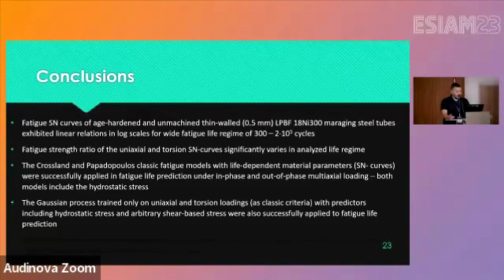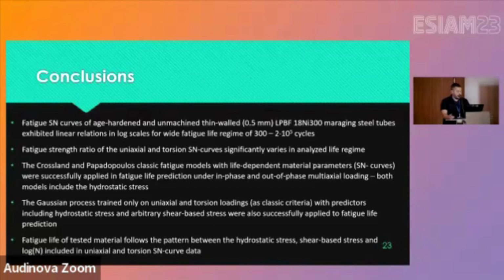The Gaussian process trained only on uniaxial and torsional loadings, with predictors including hydrostatic stress and arbitrary shear-based stress, was also successfully applied in fatigue life prediction, finding patterns between hydrostatic and shear-based stress and fatigue life, including uniaxial and torsional S-N curve data. Thank you.